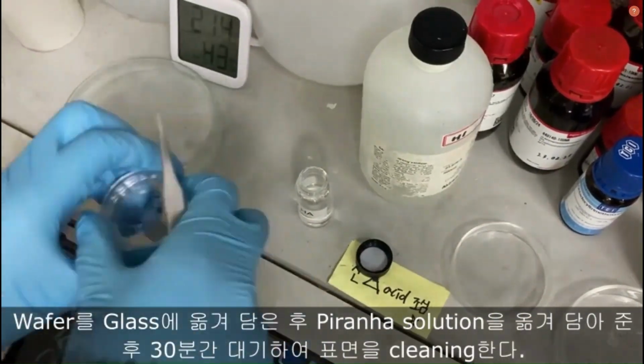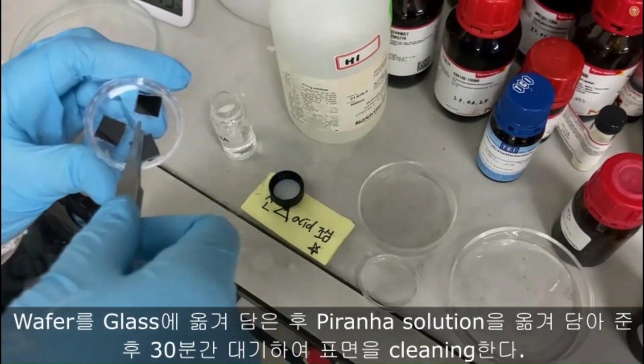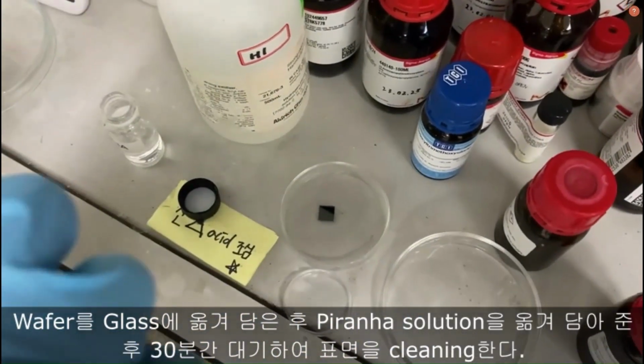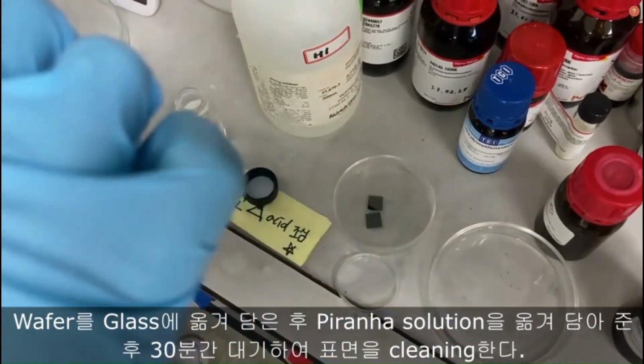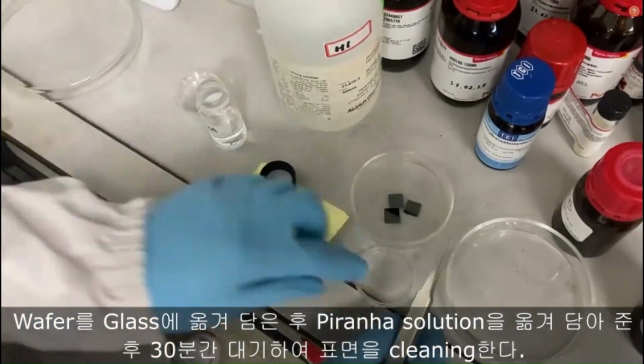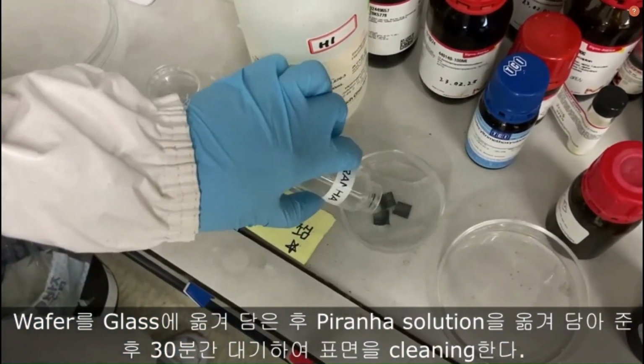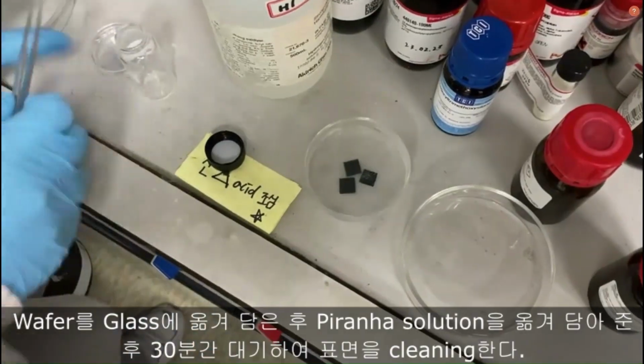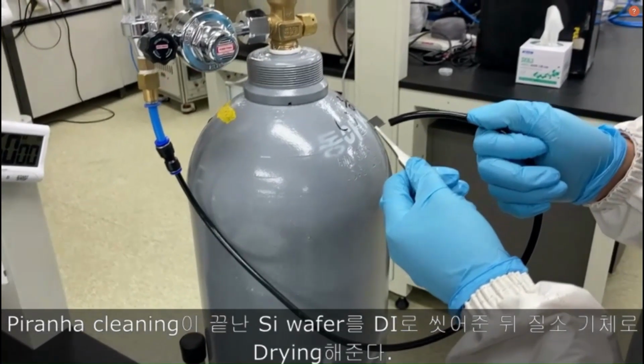Put the wafers onto the glass and pour piranha solution onto the wafers. Then wait for 30 minutes to clean the wafer surface. After piranha washing is done, the wafers are washed with DI water and dried under nitrogen gas.